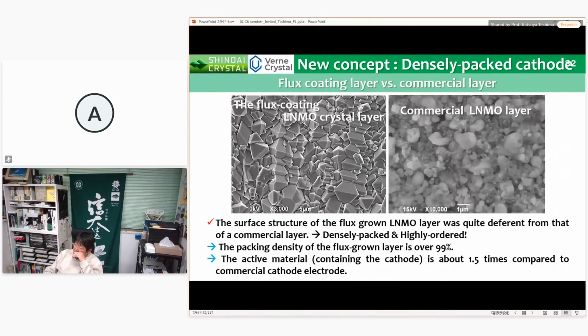These are the flux coating LNMO layers on the left side, and the commercial LNMO layers on the right side. As you can see, the surface structure of the flux coating LNMO layer was quite different from that of the commercial layer - it is densely packed and highly ordered. The packing density of the flux grown layers is over 99%, and the active material is about 1.5 times compared to a commercial cathode electrode. These are very important for improving LIB performances.